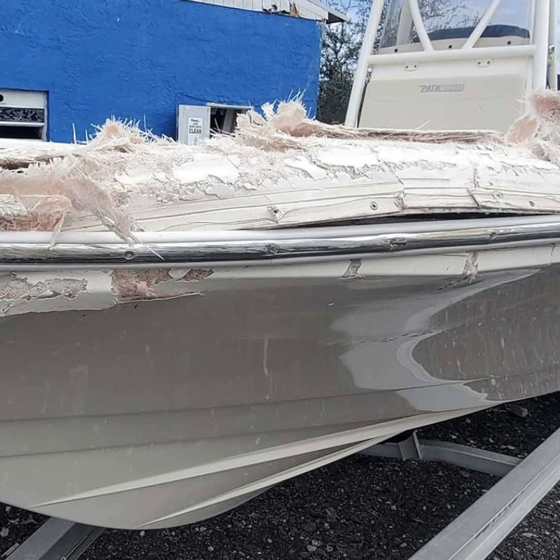And if you really want to try to clean it up as much as you can, apply some chop strand mat over the back of it while it's still wet. And that will kind of push those pleats and folds together. But basically, you can't just take a roll of woven fabric and work it over a complex shape like you can with chop strand mat. But once you get it on there and it cures, it's significantly stronger because it has continuous unbroken fibers. And you can choose the proper fabric for your job and orient those continuous fibers in the direction that the stress will be applied onto that fabric once it's cured.